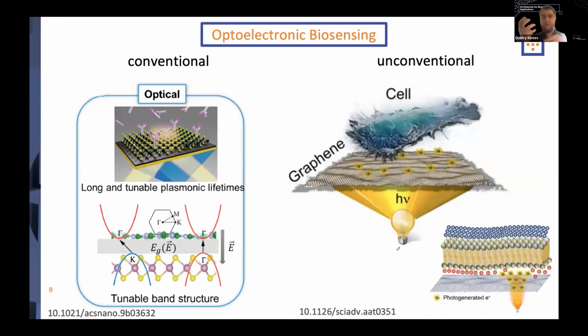If you look in a little bit opposite way, maybe not biosensing in this case, it's a little bit more on stimulation, but you can use graphene and shine UV light on top of it. Well, or in this case at the bottom, if you see. So you shine ultraviolet light on graphene, it reacts with the UV light, and it generates an excess of electrons. And then if there is a cell nearby, you might have known about the Nernst potential. So whenever you have an excess of charge on one side of an electrogenic cell, you create a depolarization of the cell. So you can actually stimulate the cell to depolarize and to create a stimulus to the cell, which is really important for many cellular applications.